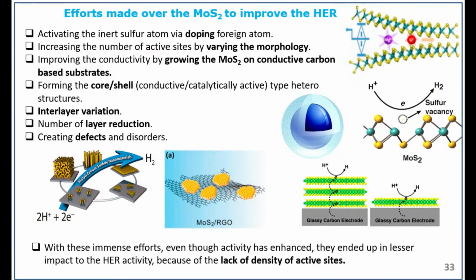So there are efforts made over the MoS2 to improve HER, because people are thinking, without going for decoration or other deposition of composite material, along with the MoS2 alone, the native material alone, how to improve the activity. There are many studies. The inert sulfur atom can be doped with foreign atoms like cobalt or nickel so that it can be activated. Increasing the number of active sites by varying the morphology can be done. But improving the conductivity by growing MoS2 on carbon is very important, because after some time the MoS2 will be detached from the carbon and the activity will go down.